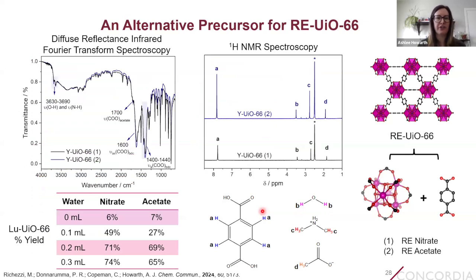Michaela also collected diffuse reflectance infrared Fourier transform spectroscopy, where you can see that whether you use the rare earth acetate or nitrate precursor, the spectra nearly perfectly overlap. We can see from the proton NMR spectra that we have all the same components. So we see the proton signals from the terephthalic acid linker, from water, from the dimethylammonium cation that balances the anionic charge of the MOF, and also from some acetate capping linkers. We also see that whether we use a rare earth nitrate or acetate precursor, the percent yield for the reaction is comparable. And we also see that in both cases, we can improve that percent yield substantially by adding between 100 to 300 microliters of water to the reaction mixture.